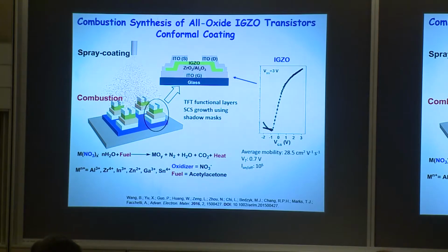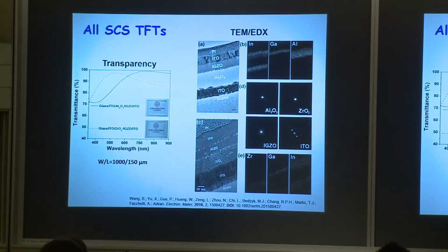Samsung told us 5 is fine for the mobility, at least for the current generation of the Galaxy and things like that. We're almost 30. It works really, really well. And Bing Hao is one of those people who does everything. So first of all, they're quite transparent. He's used, this is the alumina dielectric. This is the zirconia. This is really a Fabry-Perot effect, looking at the thicknesses of the different layers. But here with TEM and EDAX, you can see the structure is just what we claimed. It's not something else. And from the EDAX, you can see the indium layers, the gallium, the aluminum layers. You can see that the ITO gate is crystalline. The others are amorphous. So really pretty neat.